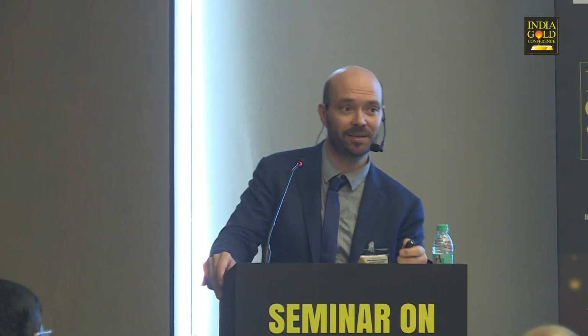Another good point is the environmental condition. You know, the microscales are very, very sensitive. So it's fundamental to keep the temperature and the humidity under control in the room where the scales are installed. These parameters are really, really important. This is because the scales can have the possibility to do an internal recalibration automatically, but they are working in a certain range of temperature and of humidity. Outside the range, the precision is not granted. Every time you get a scale, you receive the certificate that is issued by the manufacturer. There you can find some parameters that are fundamental, that are giving you the performance for a specific weight, for a specific scale.